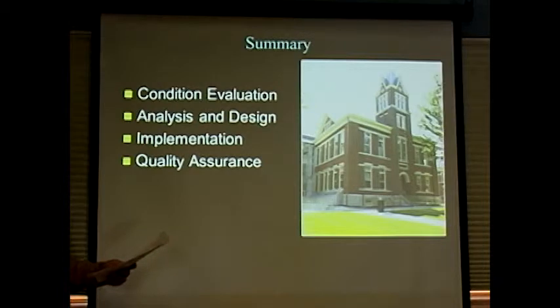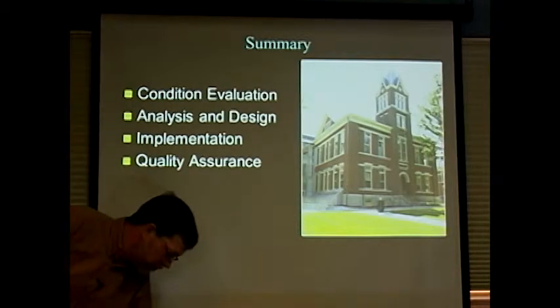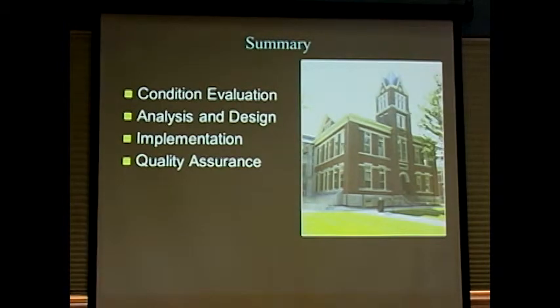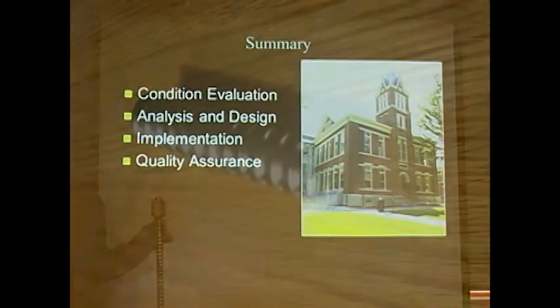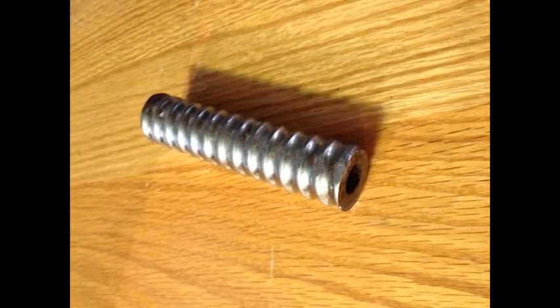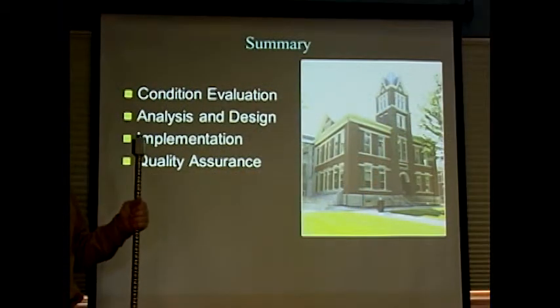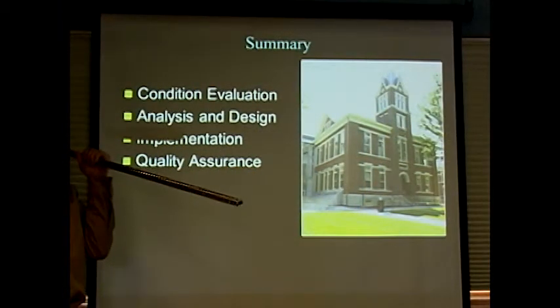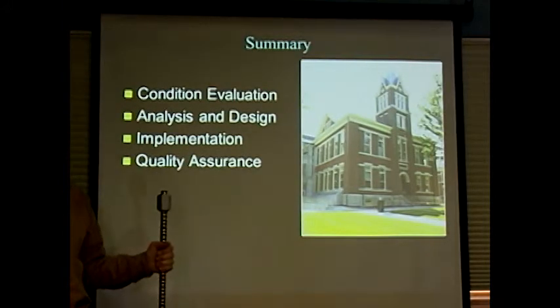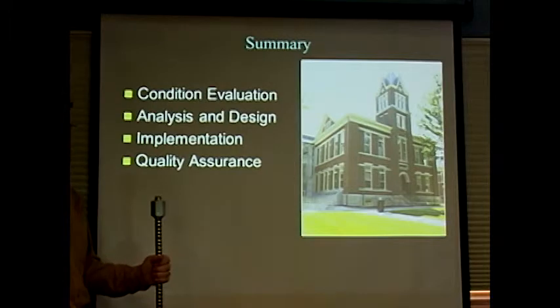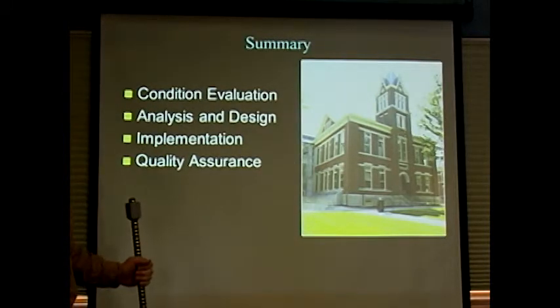So that's it. I had a couple of final thoughts, in thinking about how we would do this differently. Well, I'll tell you, we have some new materials now. We've worked with Masonry Solutions. They actually bought a device, a big cold rolling system, that will take these stainless steel tubes and turn them into deformed bars. We've been doing a lot of work in New Orleans lately, strengthening pump stations, and this is one of the bars they put in by the thousands in pump stations in New Orleans. They take a stainless steel tube and cold roll it, and that's interesting because you go from about a 30,000 psi yield to 70,000 psi through the cold rolling process. Plus you get the deformations that grab onto the grout better.